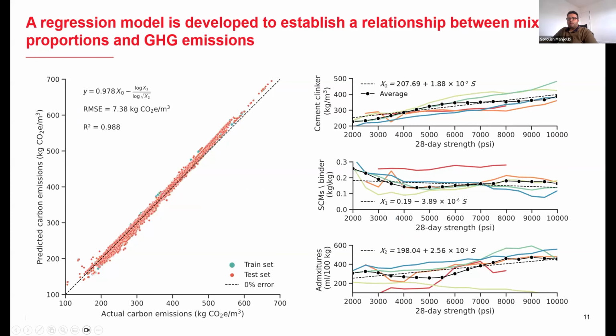So here we have developed a simple symbolic regression model to establish a relationship between mix proportions and GHG emissions. On the left-hand side, you can see the goodness of fit for this model, and the root mean square error is about 7 kilograms CO2 per cubic meter. On the right-hand side, these figures represent the relationship between the 28-day strength, which are the observed ones, versus the cement clinker, SCM percentage, and admixture dosages. And each line color represents a company.